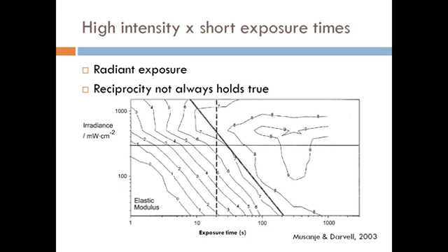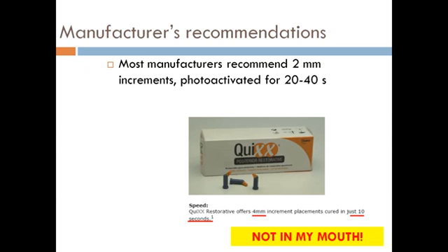is that even for the light sources that you have here in the pre-clinic, those are putting out 2,000 milliwatts per centimeter squared. So you do not want to keep those on for more than 10 seconds, 10 to 15 seconds. You're not going to use 20 seconds for those because they're very powerful. And they are, but you don't want to keep them on for only 2 seconds either, exactly because of this that I'm just explaining to you. All right? Because you're not going to get to the properties that you need.